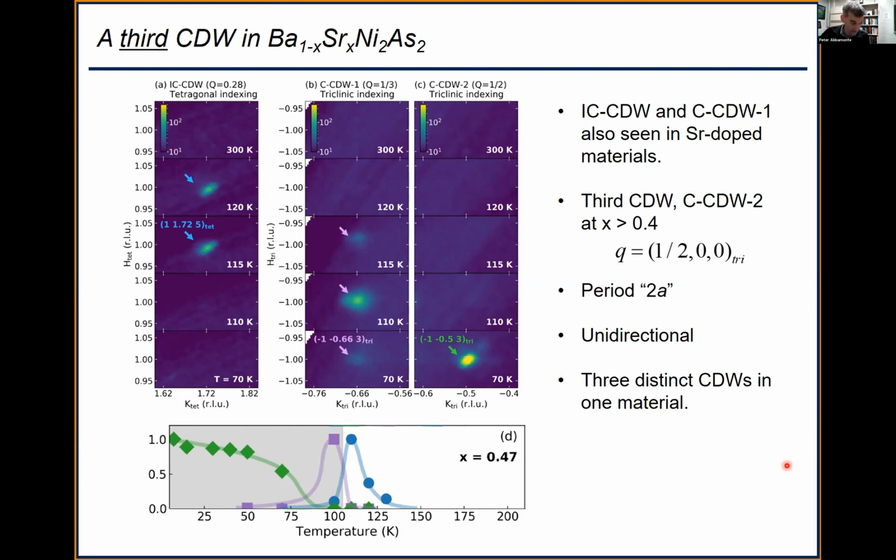I have several answers. The first answer is, I have a hunch, I can't prove it, but I believe this incommensurate phase is dynamic. I need a different plot, but one thing this doesn't show is that this blue line is about a factor of 50 smaller than the purple, and the purple is about a factor of 10 smaller than the green. So what really is happening is as you cool toward the triclinic transition, there are fluctuations building up at a wave vector of 0.28, like it wants to form that phase, and it's still dynamic and hasn't asserted itself, but before it can form, it gets preempted by another phase transition with a different order, and then this thing is really static. Some very low frequency fluctuations, presumably. Yes, this is an energy integrated measurement.